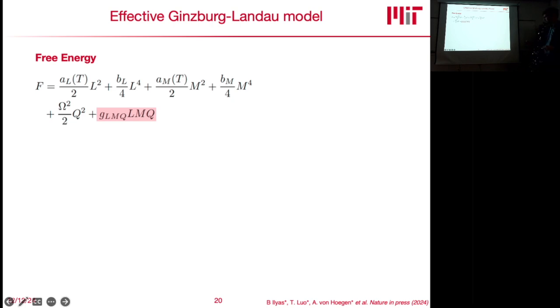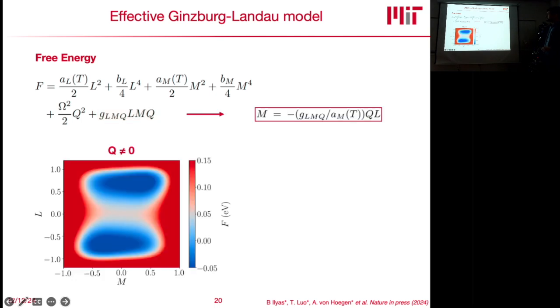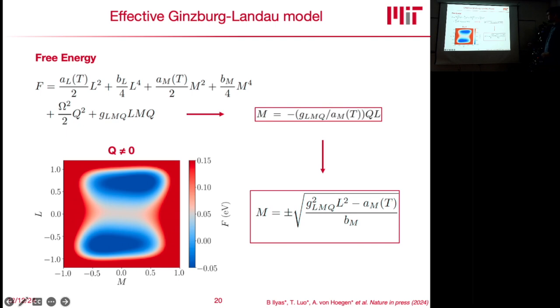We cast all of this into this effective Ginzburg-Landau model, where we couple with this additional term. What this gives rise to is that at a finite displacement of these phonons, you start creating finite magnetization minima here, basically shifting these minima away from zero magnetization into a finite magnetization. And so you can solve all of this self-consistently. This is exactly what I mentioned before: once you displace the phonon, you create a magnetization, but this magnetization then in turn would displace the phonon. So it's a self-amplifying, rather self-stabilizing process.